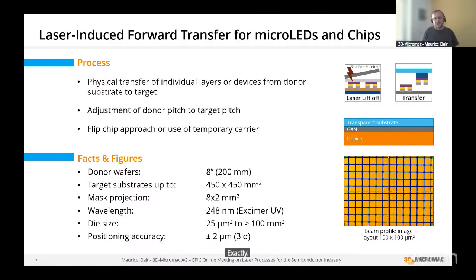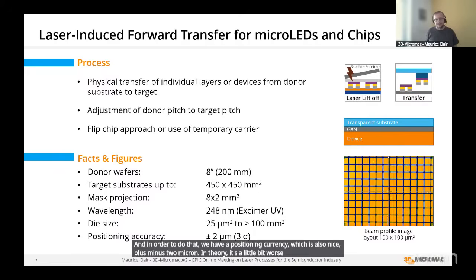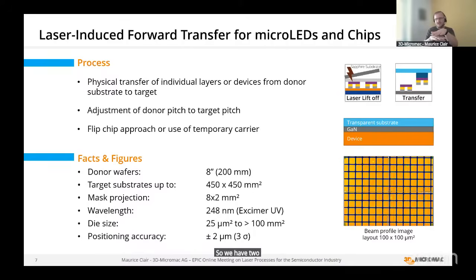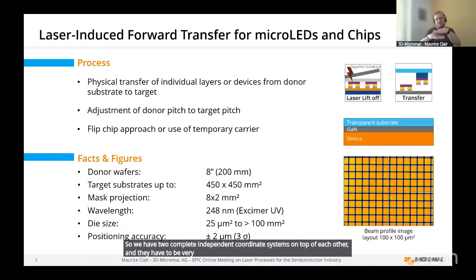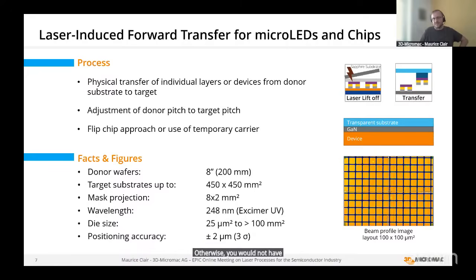Exactly. And in order to do that, we have a positioning accuracy which is also nice, plus minus 2 micron. In theory, it's a little bit worse than the other tool with 3 sigma, but here you have to remind ourselves that we not only have one wafer which needs to be positioned, but we have the target and the donor. So we have 2 complete independent coordinate systems on top of each other, and they have to be very close to each other. We talk about transfer gaps in the range of 50 to 100 micron, and in the total XY direction, plus minus 2 micron. Otherwise, you would not have a successful transfer of the micro LEDs. So also a very nice system.